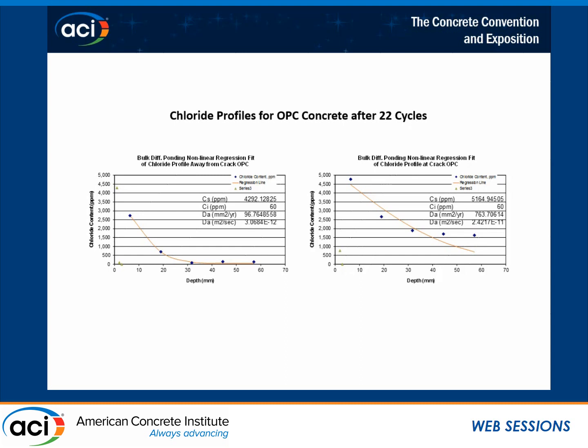We get an estimated apparent diffusion coefficient of about 3 times 10 to the minus 12. At the crack, we can see obviously about the same, more chloride present, and it doesn't come down quite as much. It looks like the diffusion is going up by an order of magnitude. But it's still reducing chloride coming in the crack compared with OPC.